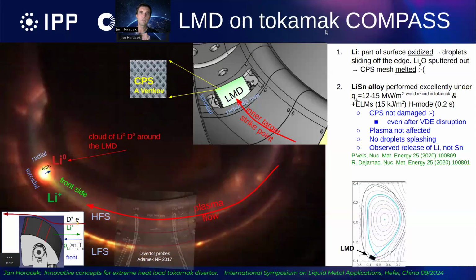What we showed in 2019 on COMPASS, for the first time, we were testing a liquid metal little module on the bottom of the divertor, just a 4 centimeter large module. We put it as perpendicular as possible to the plasma to receive as high heat flux as possible with our relatively weak plasma, let's say. So we achieved values between 12 and 15 megawatt per square meter without any damage. No damage for the lithium-tin alloy plasma-facing component. And it survived even ELMs in the H-mode and vertical displacement event disruption. The plasma was not affected by this, even though we saw quite a lot of radiation from the target. And there were no droplets splashing. And also we observed release of lithium and no tin, which is very important.